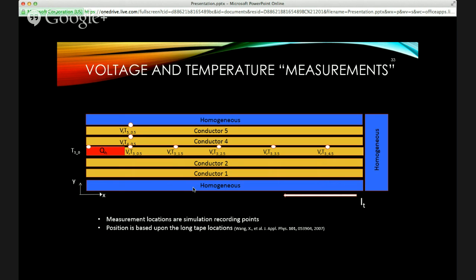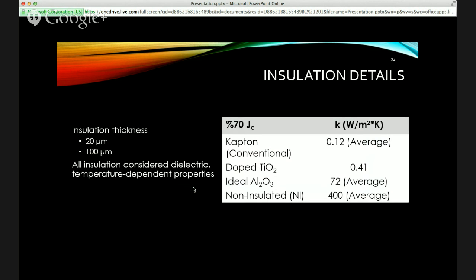So if you could imagine, the current is coming from the right direction and flowing towards the hot spot. Keep that in mind. I mentioned the insulation materials. I actually looked at two different thicknesses, 20 microns and 100 microns.